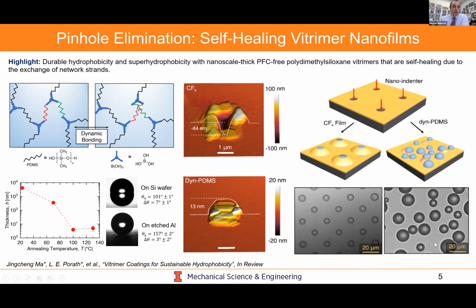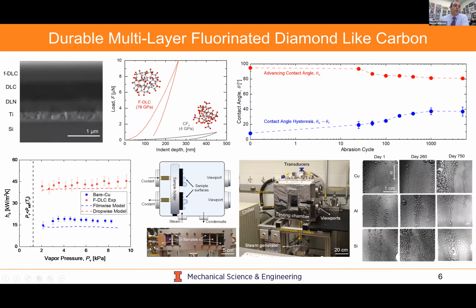Now, if you want to come at the problem from the material standpoint, we've also been looking at enhancing those material properties by developing multi-layer fluorinated diamond-like carbon. We use multi-layer because it gives you the functionalities that are required to get you to the material properties that you need. In this case, we use titanium interlayers for great wet adhesion. We use different compositions of DLC layers to give us thermal stability. And then we have a bulk layer on top of co-deposited fluorinated DLC, which gives us our low surface energy.